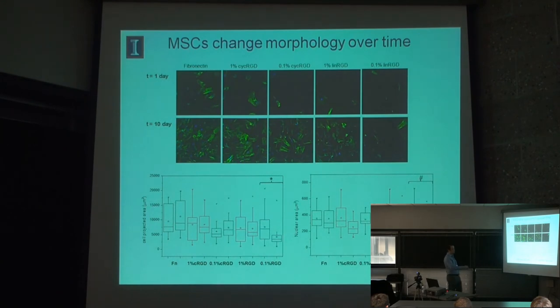And then finally, at this very low density peptide surface, many cells start to look a little neuronal. And I'm not going to claim that these are neurons, but similar to what Adam Engler had shown, these processes being extended was one of the hallmark characteristics. And so I should point out, too, when we quantitated these shape changes, the low density was really interesting, where we see that after 10 days in culture, we see a significant decrease in cell area as well as nuclear area. And when I see a change in nuclear area, that tells me something's going on with gene expression, and maybe the chromatin is condensing and some other program is going on.